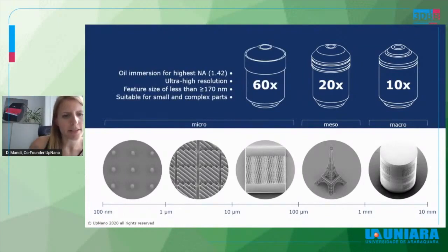The third one is the one with the highest numerical aperture of 1.42, and it's in this case an oil immersion objective. It's used for ultra high resolution and feature sizes down to approximately 170 nanometers. And it is suitable for structuring small parts and very complex parts. So the 60x objective is not intended to be used for the cylinders, for example, for printing 5 times 5 millimeters, but really for small micro tags, like you can see on the left side, or surface elements where you have some defined elements on top, and also for grid structures, for example.